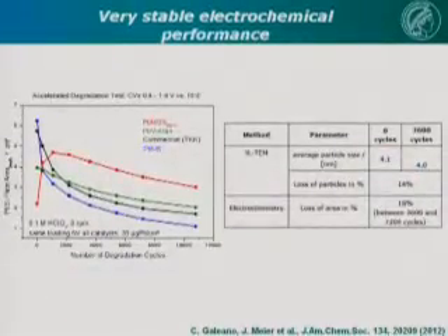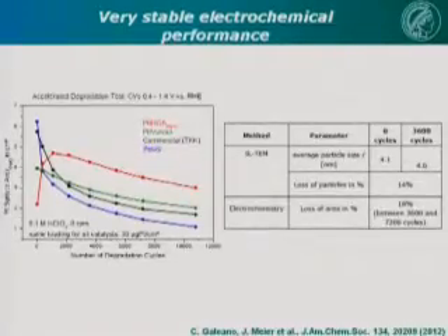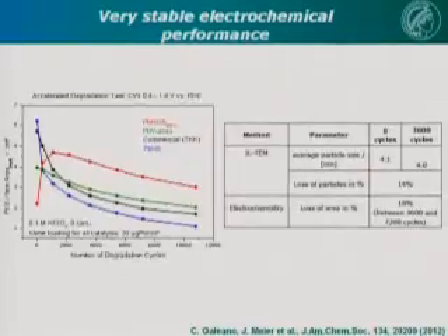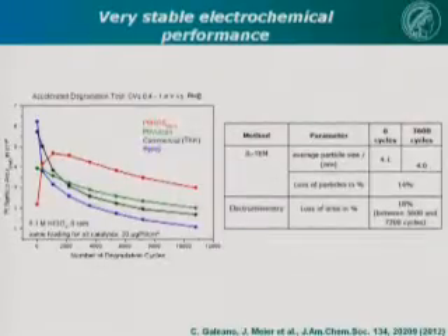And what we then see is, compared to commercial catalysts, this is the aging profile over many degradation cycles, 12,000 accelerated degradation cycles in this rotating disk setup. It deactivates actually quite rapidly, while this platinum on hollow graphitic spheres has about twice the activity after the degradation test of 12,000 cycles. And if we analyze from the electrochemistry, we lose 18% of the platinum surface area during these tests. And if we analyze by identical location how many particles we have lost, we lose 14% of the particles.